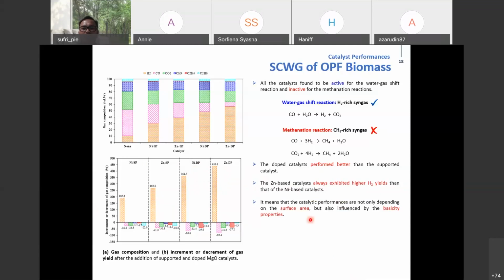So why is the zinc better than the nickel? In literature, most research focuses on the surface area. But the surface area is not the only reason the catalysts are active in the reaction. There is another factor that influences the reactivity. If you still remember, zinc has a lower surface area compared to nickel, but in this case, we prove the zinc performs better. So what is the reason? Because, from the TPD ammonia results, the zinc exhibited a greater amount of basic active sites, of medium strength, compared to the nickel DP and also nickel SP. So surface area plus basic properties is the extra advantage for the catalytic reaction.